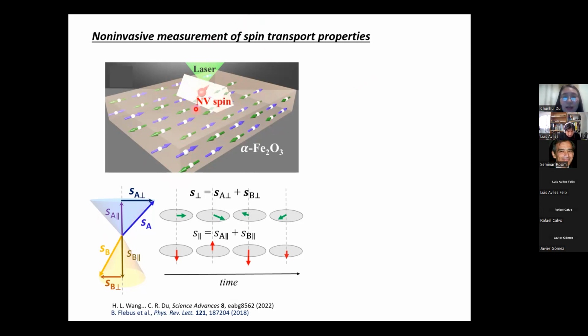In order to understand the spin fluctuation, we can use this schematic. We can separate the spin fluctuation into two main categories. The z-axis here is the Néel order. So we have the transverse spin fluctuation that happens perpendicular to the Néel order, as well as the longitudinal spin fluctuation that's parallel to the Néel order. The transverse spin fluctuation has the same frequency as the antiferromagnetic magnon. In alpha iron oxide, the band gap of the magnon is about 160 gigahertz. This frequency is much larger than the few gigahertz NV electron spin resonance frequency. So we basically cannot probe the transverse spin excitation using NV center.